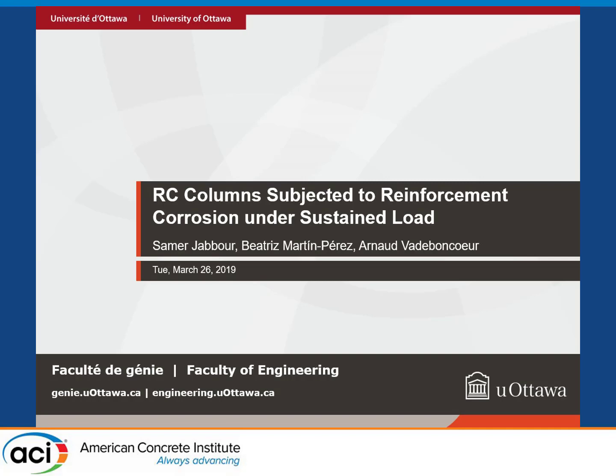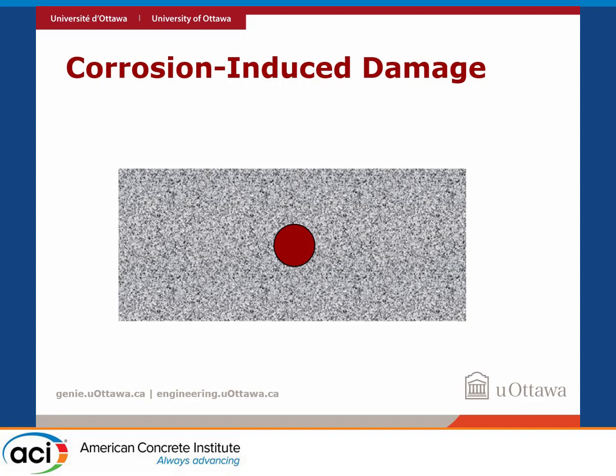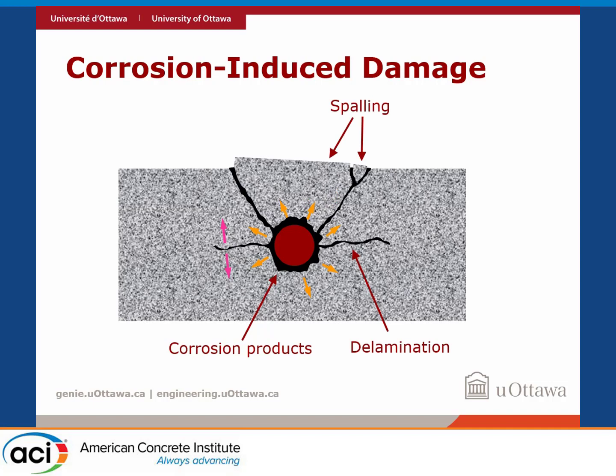Concrete in general provides a very good protective environment for steel because it has a high pH due to the hydration of cement. But if enough chlorides come into the concrete, or carbonation of the concrete cover happens, the passivity that naturally occurs in steel within that high pH environment is broken, and then corrosion of the steel starts. Provided there is enough oxygen and water, that corrosion creates corrosion products. They have a lower density and higher volume, and eventually they exert a pressure around the reinforcing steel. Concrete cracks, and those cracks can develop, creating spalling and delamination of the concrete cover.